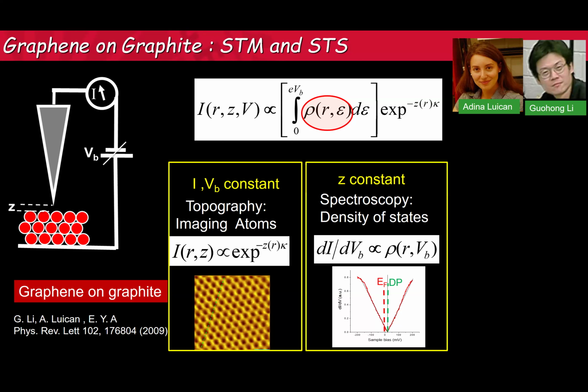Oh, sorry, it's kind of a stupid question, but what's the difference between graphene on graphite and just graphite with another layer? Okay, so with graphite with another layer, you see all the other layers. So the dispersion changes. You don't have Dirac cones. So if you want to see graphene, you have to suppress the tunneling into the bulk. And that you do, because it's exponentially dependent on distance, it's enough here, we were 20% above, larger than the natural separation. When you go to natural separation, I don't have the paper here, it's very different. Okay, thanks.